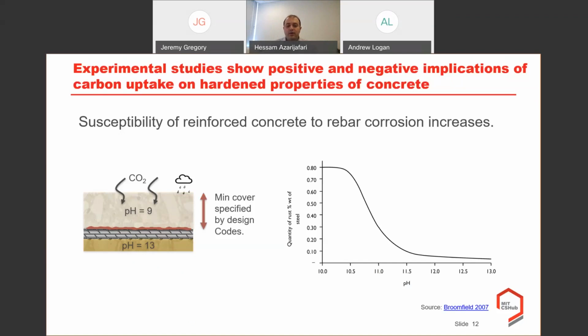So that's why we observe in some of the design codes there are some minimum cover specified for concrete structures. But what I should note here is that the carbonation alone is rarely a source of concern for lifetime, let's say below 50 years, unless concrete quality is very poor and the workmanship is also poor, like insufficient concrete cover as we discussed. But for very longer lasting structures, carbonation must be taken into account and must be modeled in the rebar corrosion and the possibility of the minimum cover specified by these design codes.